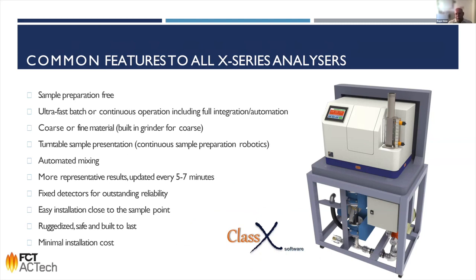an individual sample. We connect our analyzer directly via this tube with a sampler. Of course, we can also do multiplexing to connect it to two samplers to switch between different sampling points. And the material is processed through the analyzer, analyzed in real time. And the material either can be collected for subsequent tests in the laboratory or automatically returned to the process. So it runs fully without human interactions.